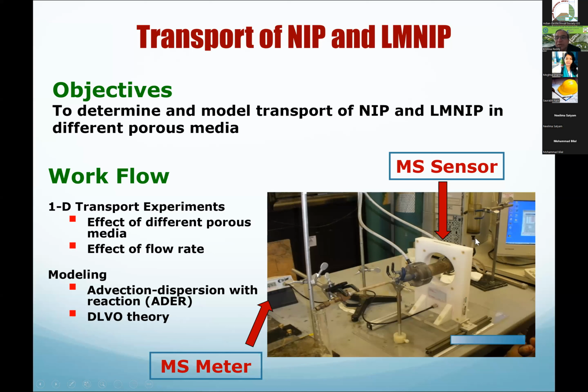There's a top reservoir where we are injecting from one end, and we are collecting the effluent from this end. And what we have here is this magnetic susceptibility sensor. Basically, it can sense the iron concentrations. The problem is, when we're flushing, we want to know how the nanoiron particles are transporting. How do we know that? You can run for a longer period of time, then all that iron will come out here, right? But if you want to know how it is migrating through the sand, you have to do experiments at different times, take it out and section it. Can we monitor non-invasively, right?